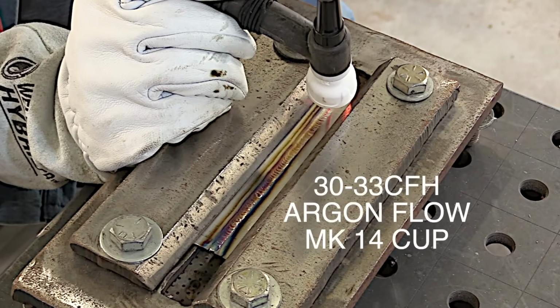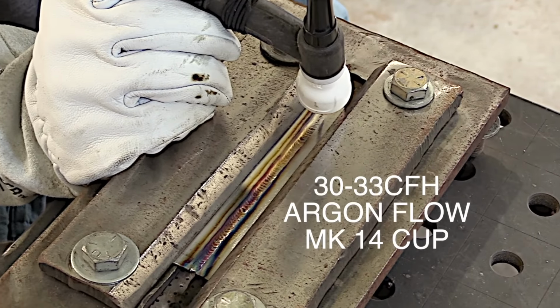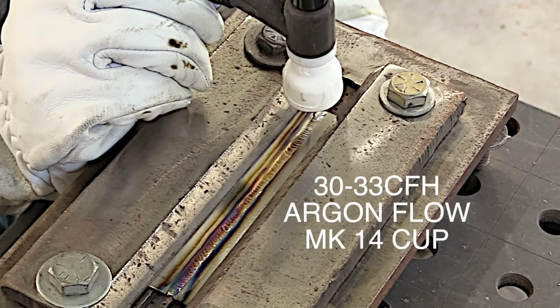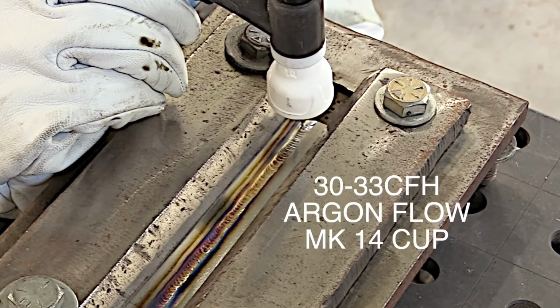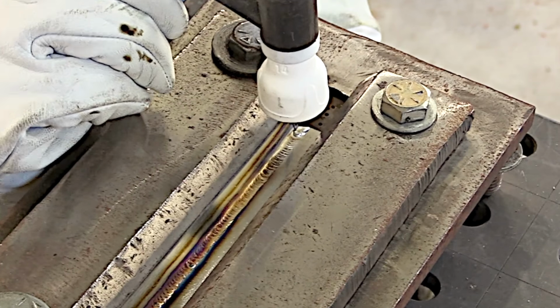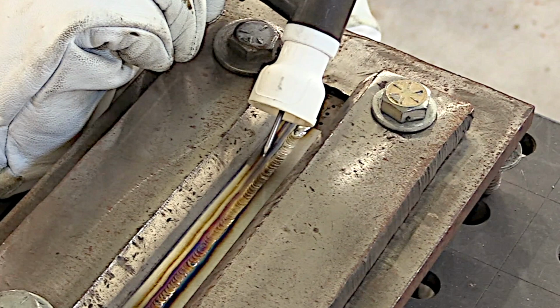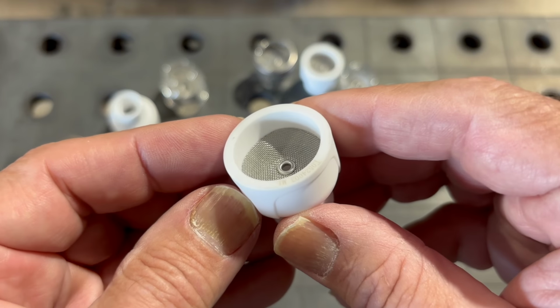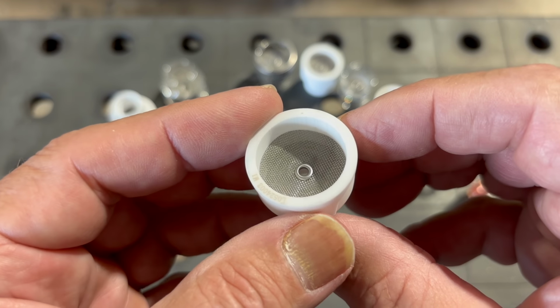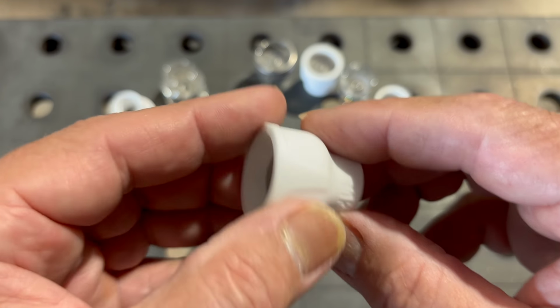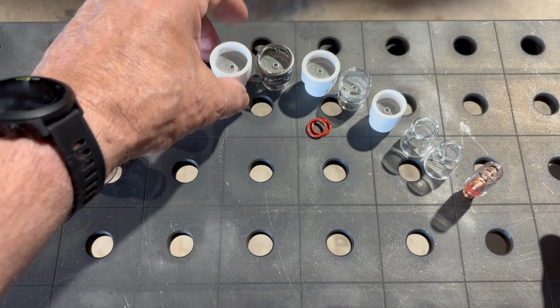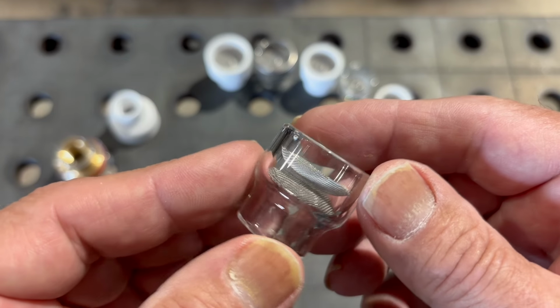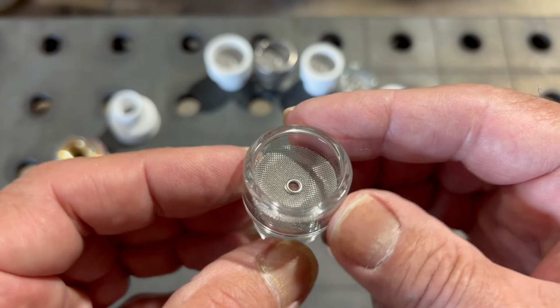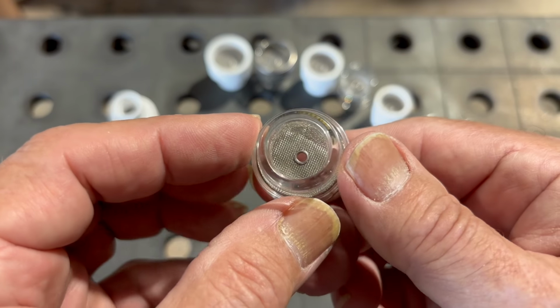While I was training and testing welders for Delta Tech Ops, we kind of stumbled upon a cup that was made by a mom and pop outfit that was similar in size. We could hardly get them. We used those cups for test welds of stainless, nickel-based alloys, titanium, cobalt-based alloys, but they became really popular in the hot section shop, in the general welding shop, even in the blade and vane shop, in the stator shop. And the reason is that they tend to clean up the weld when you're welding the kind of alloys that you weld in aerospace that have small quantities of aluminum and whatnot in them for hardenability, for precipitation hardening.